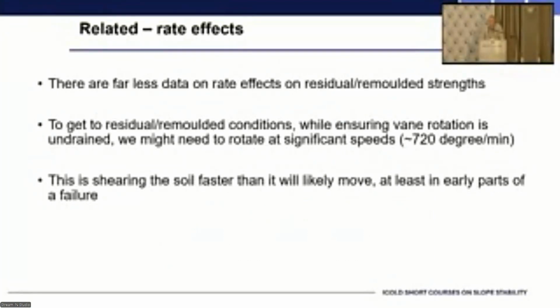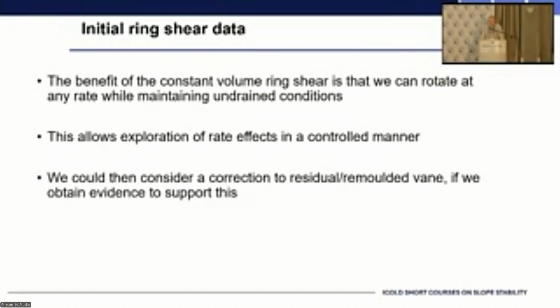Compare that with the conventional rates that the vane is specified at, much, much higher. But just note that that's then applying a shear rate which is much faster than we'll probably see in a failure condition in the field. So is that perhaps being unrealistic in terms of rate effects again? So when thinking about the need to capture this post-peak behavior, there's a lot of complexities involved.